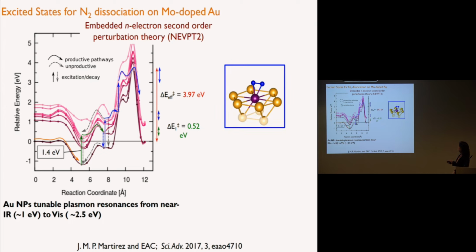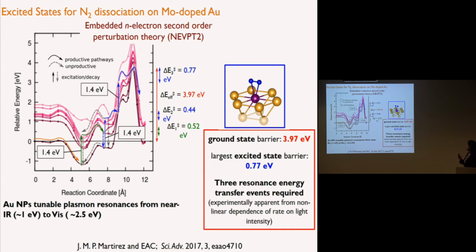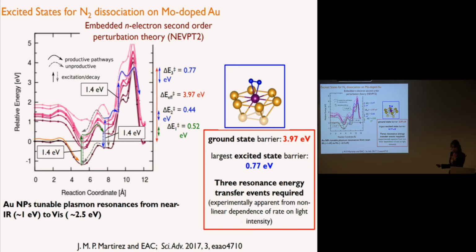And that's essentially brought us to a point where you can undergo another excitation that allows for this reorientation to happen with a barrier of less than half an electron volt. Then one more pump up can get us to a point where the barrier to get finally to the state where the nitrogen is fully dissociated is 0.77 electron volts. Essentially the largest excited state barrier that has to be overcome is this. This is a prediction, and hasn't been borne out experimentally, but it is a huge reduction in the barrier.